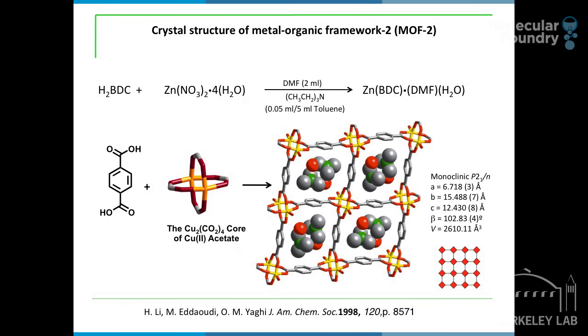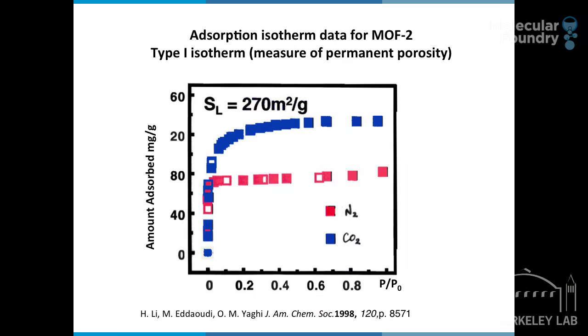And there, as an inorganic chemist by training, we found in my group that the linking of simple links such as terephthalic acid, when it's deprotonated as terephthalate, links to zinc-2 ions to make a beautiful grid-like structure based on, now instead of single metal corners or intersections, multi-metal rigid clusters, and that did the trick. And that is that now, upon evacuation of the solvent molecules that filled the pores to make a porous structure, we found that they can take up gases such as nitrogen and carbon dioxide to give a typical type 1 isotherm. When I say typical, I mean typical of porous materials such as, in those days, the traditional porous materials such as zeolites that were known to be truly porous.